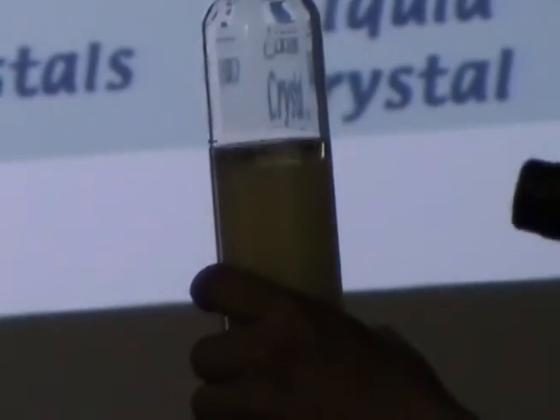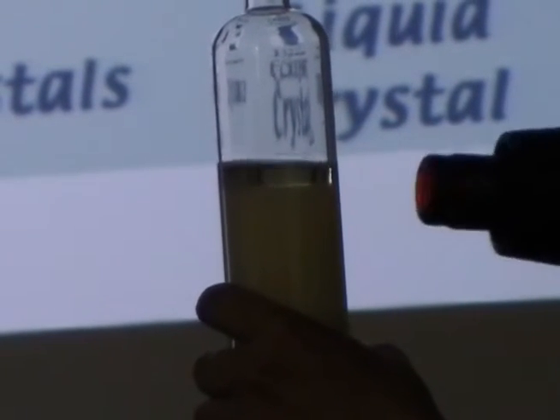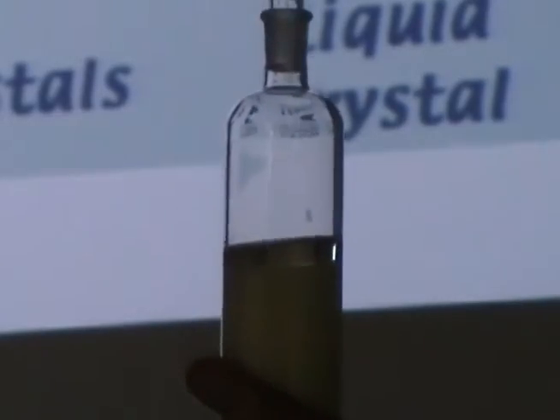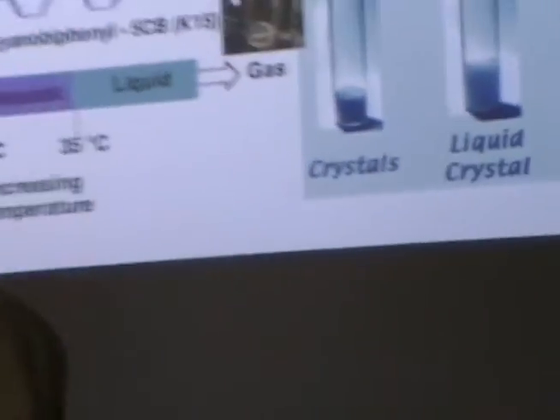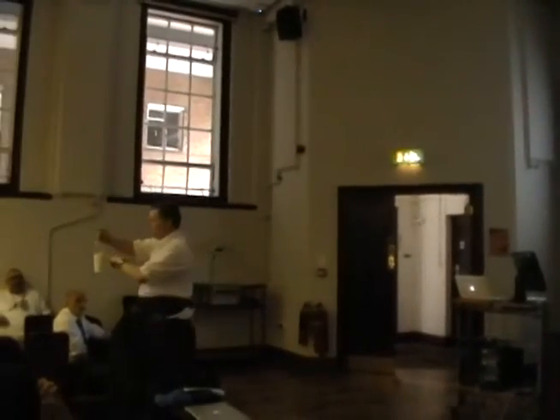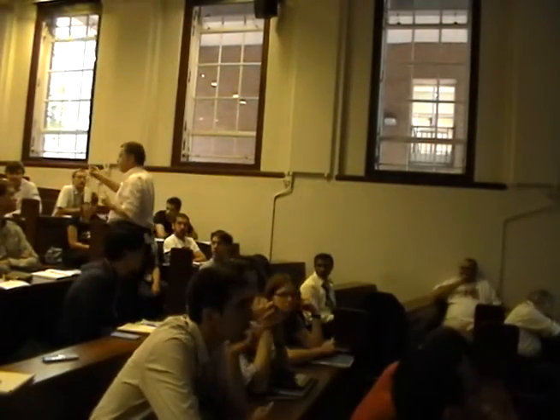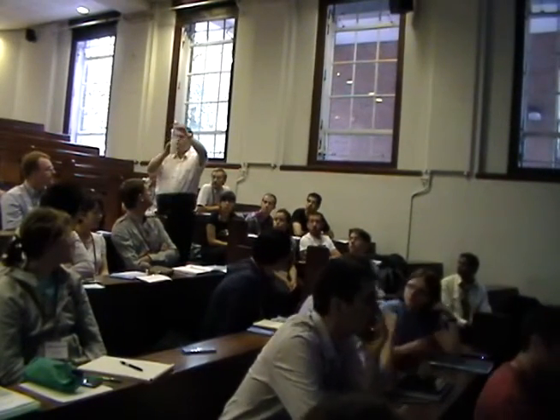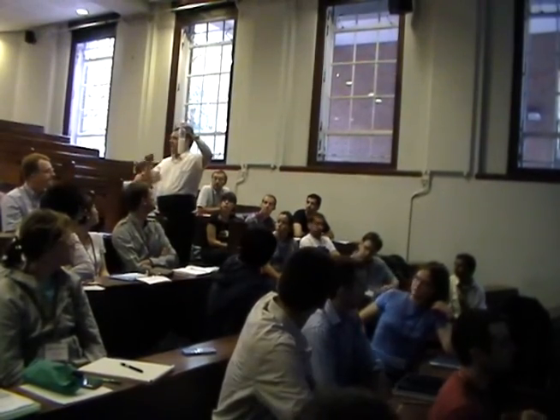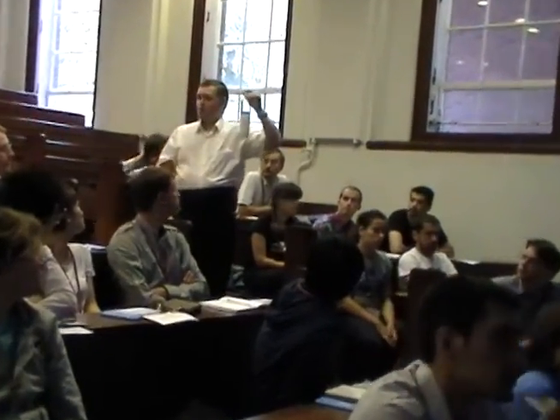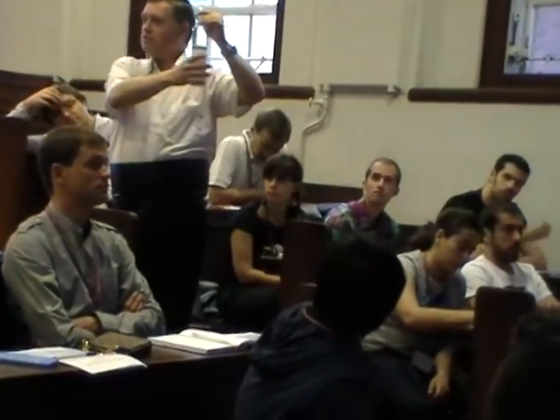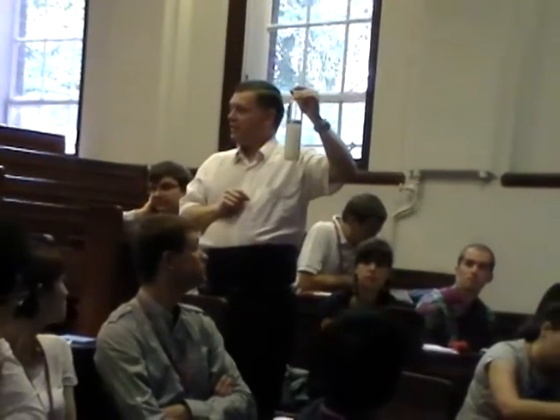Okay, so those of you at the front should be able to see this start to change now. I'm going to wander around and just come to the ends of each of the benches and you can see. So you can see at the bottom here we're still in the nematic phase. At the top here, this is now completely transparent. This is where it's disorganized. It's in the isotropic liquid. And so, those of you that can see, there's a very sharp boundary between the two. And that boundary is the clearing point of the liquid crystal. So this is the temperature at which we go from being liquid crystalline, so being nematic liquid crystal, to being isotropic liquid. So this is just a well-defined temperature.